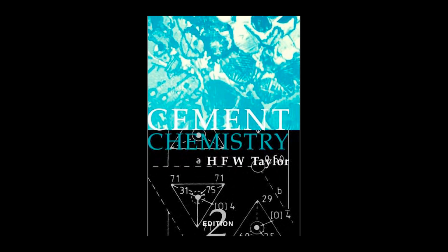Okay, so all these microstructural components, the CH, the CSH, the unreacted grains, they form this massive composite material that is inherently porous. And this porosity is the single greatest determinant of long-term durability. How do we categorize it? We use the foundational Powers-Brownyard model. It defines the total porosity as the sum of two types: gel porosity, which are the extremely fine micropores within the CSH itself, and capillary porosity, which are the larger spaces that were initially occupied by the mixing water that weren't filled by hydration products.